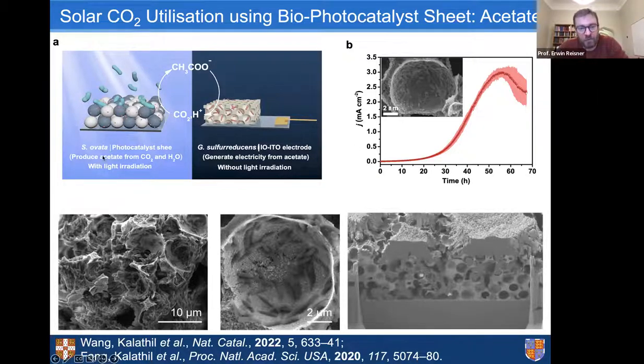So if we couple these two together, we get acetate from the photocatalyst sheet. And then as we start accumulating acetate, at some point our microbial fuel cell switches on and starts to produce a current. So it shows really we can accumulate acetate, and enough acetate to drive a microbial fuel cell to produce electricity.